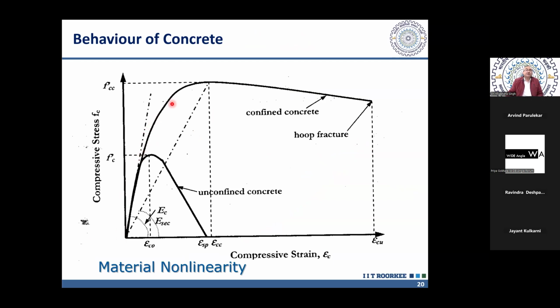So here the behavior of concrete is shown. So we see the stress strain curve. This lower one is the stress strain curve of unconfined concrete. In case of unconfined concrete, the peak occurs at a strain of roughly 0.002 and the failure occurs at a strain of 0.005. In our code, we consider it to be flat up to 0.0035. So in place of this behavior, we consider an idealized behavior like this. But what you see here is that the ratio of ultimate strain to the peak strain is less than or equal to 2, 0.0035 divided by 0.002. So there is very small inelastic range of strain in case of unconfined concrete.